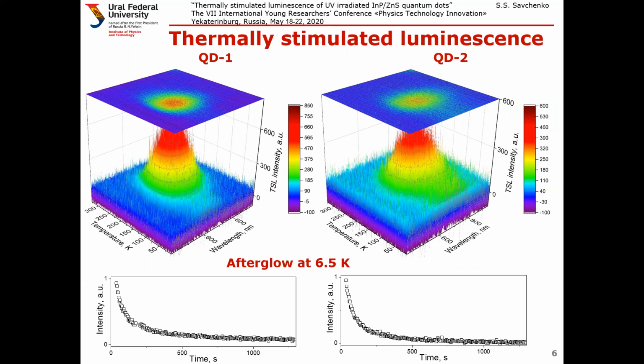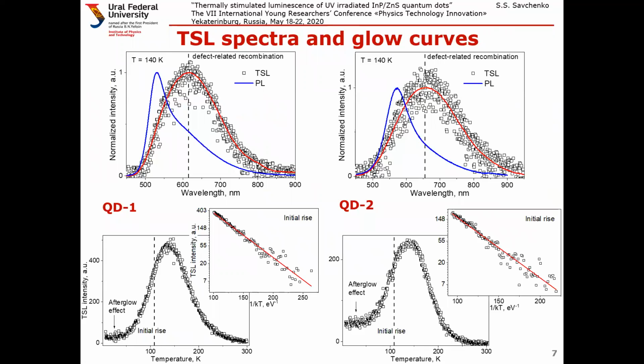Even at low temperature, after irradiation had been turned off, we've detected long-lasting afterglow effect. As you can see on the upper plots, it wasn't vanished during the subsequent heating. Spectral resolution allows us to conclude that recombination centers revealed in TSL experiment correspond to emission via defect-related states observed upon cooling in photoluminescence. Glow curves for the maxima spectral regions are shown on the bottom plots.